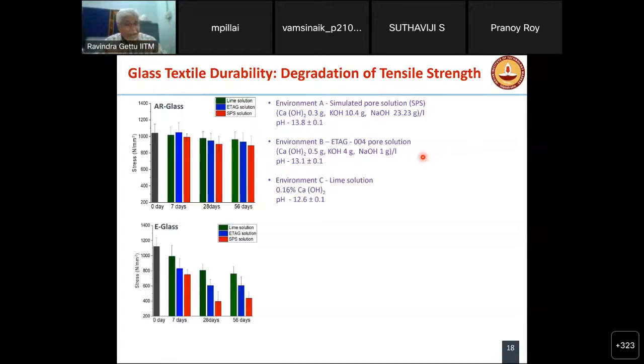So here I have values of tensile strength or the peak tensile stress going down due to exposure to different solutions. Here we have different solutions, but with different pH values, simulating what could happen in cementitious binder. We find that if it's AR glass, alkali resistance glass, then really nothing happens. The textile behaves quite well.